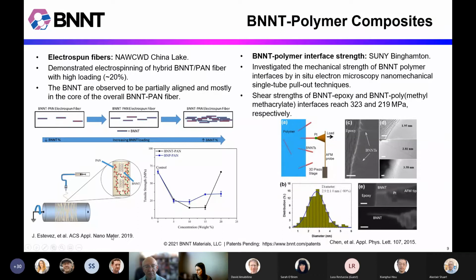So what they reported here a couple years ago in 2019 was the observation of this percolation threshold. So this is strength and this is concentration of nanotubes. And if you follow this black curve, you can see that at some point the properties start to improve dramatically. And that's what they're working on now. And they've actually, I think, improved this weight loading even further beyond the 20%.